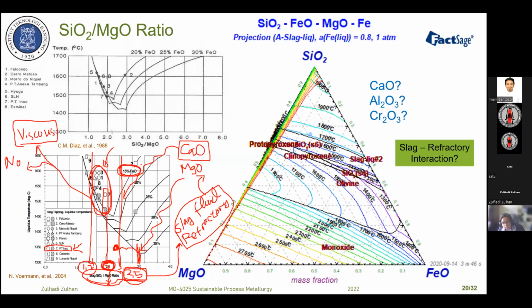The maximum iron oxide content in slag for the current operation of the furnace is around 22%, between 20 and 25% is the maximum in this range. If you see from the data, there are only 2 plants in the world operating with high iron oxide content. The other plants try to operate the electric furnace with iron oxide less than 15%. In some cases, for example when they produce NPI, nickel pig iron, they want to take more iron. The iron content in the product should be high. In that case, the iron oxide content could be less than 10%.